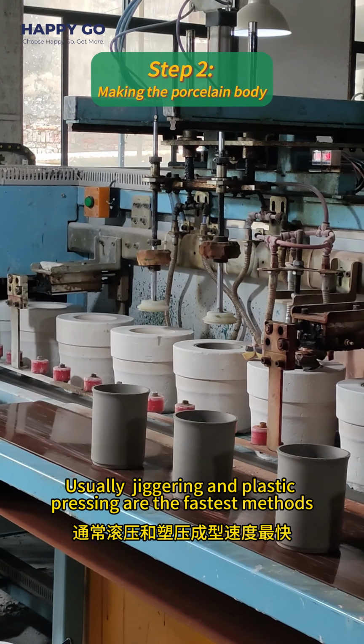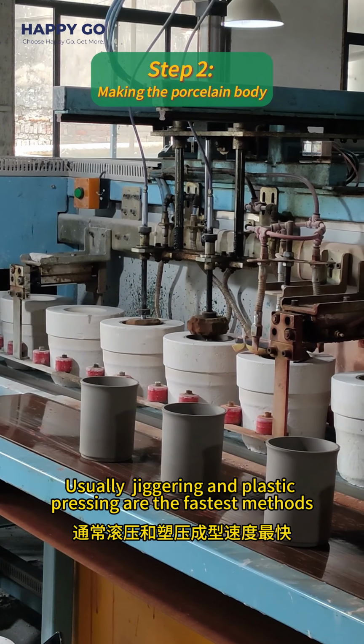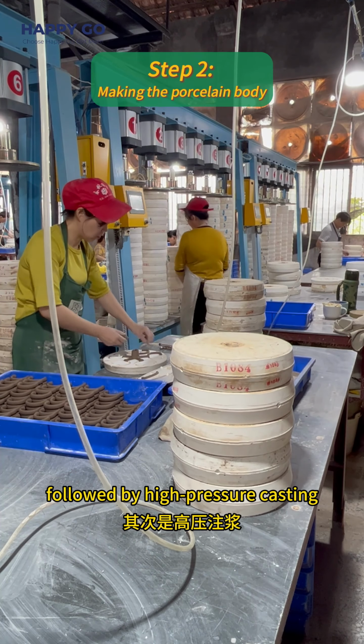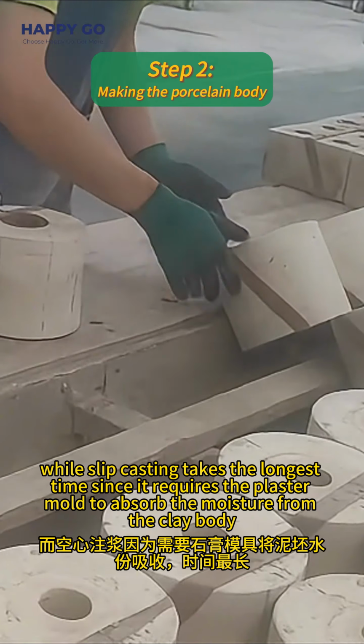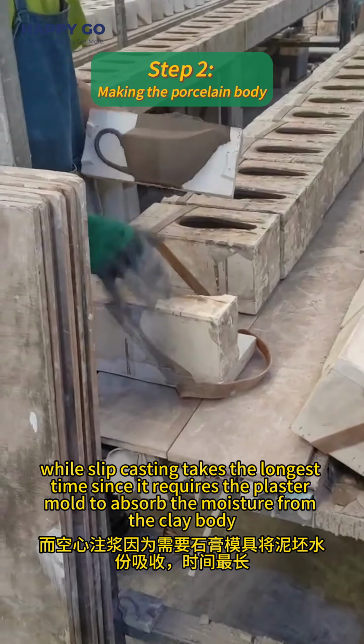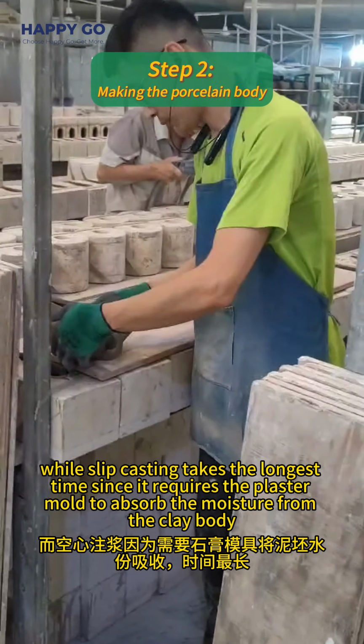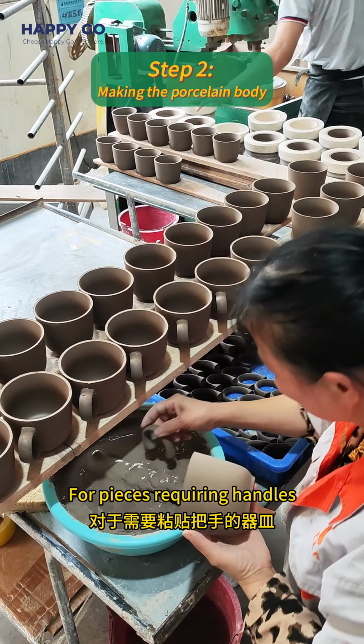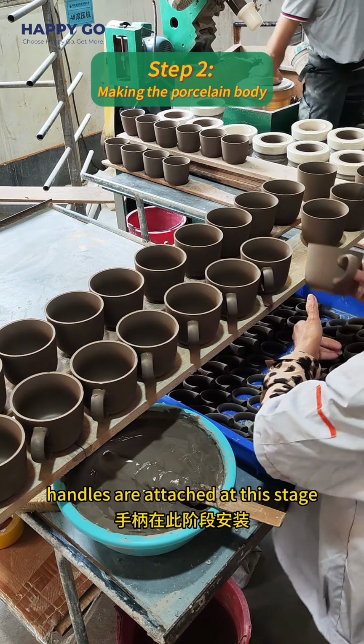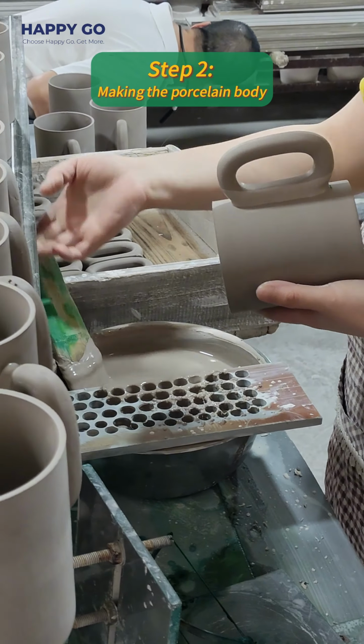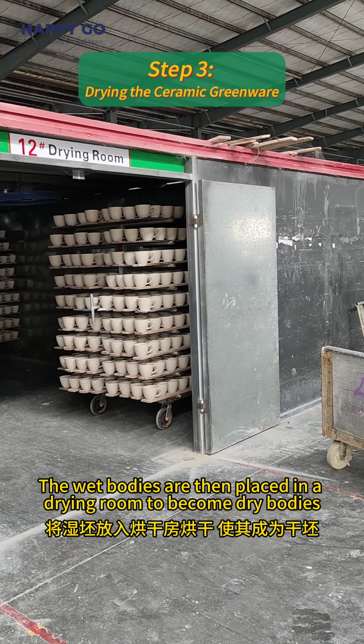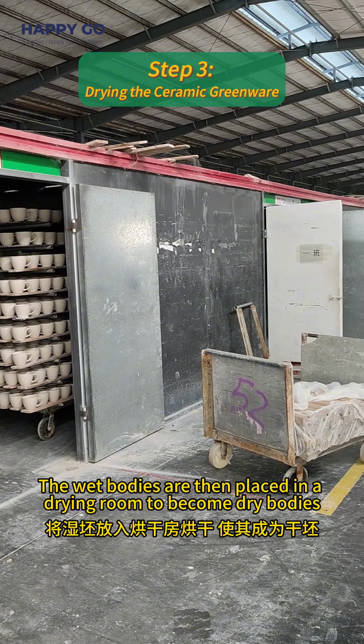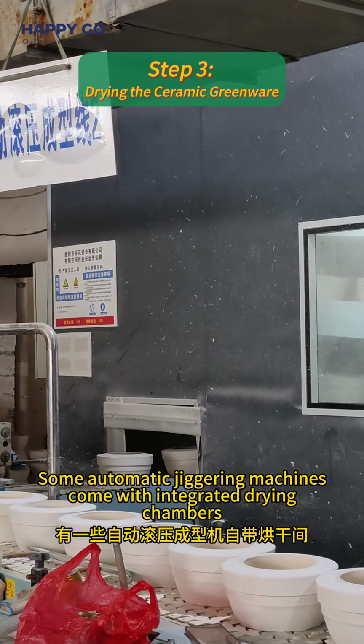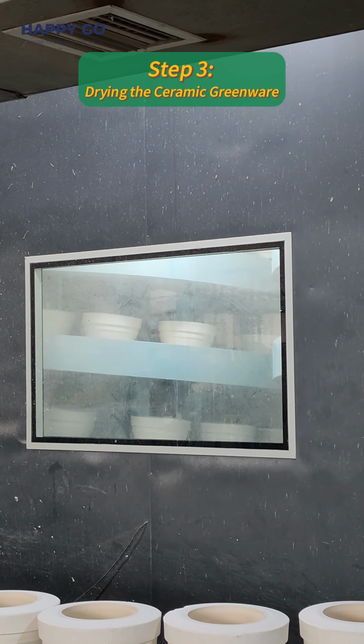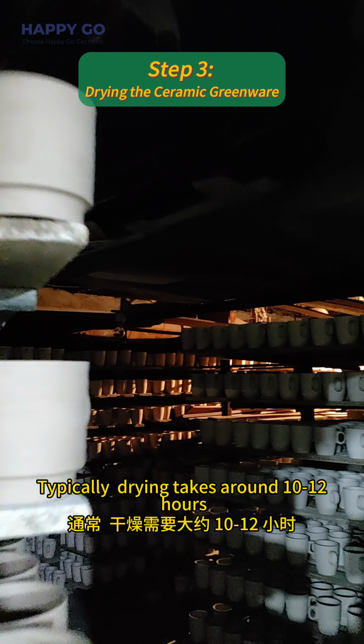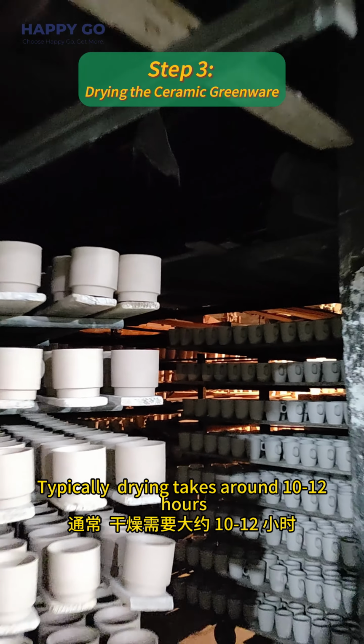Usually, jiggering and plastic pressing are the fastest methods, followed by high-pressure casting, while slip casting takes the longest time since it requires the plaster mold to absorb the moisture from the clay body. For pieces requiring handles, they are attached at this stage. The wet bodies are then placed in a drying room to become dry bodies. Some automatic jiggering machines come with integrated drying chambers. Typically, drying takes around 10 to 12 hours.